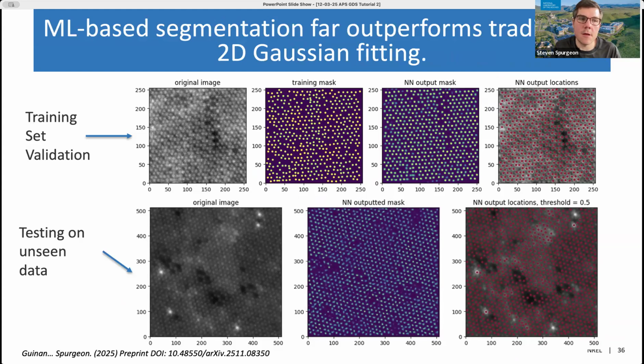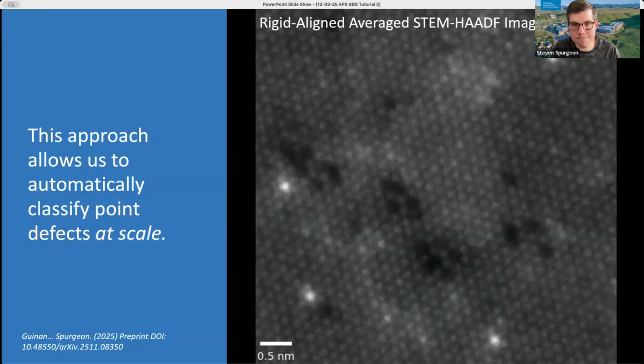And so what you're seeing here along the top is a training set validation looking at the input image, training mask, the output mask, and then the calculated positions. The bottom here is showing that we can test on unseen data and get really good performance relative to the 2D Gaussian fitting. And the key here is that this model scales. It scales to scenarios of noise, regions that might not be at the exact same orientation or illumination of the sample. And so this is a very powerful approach relative to the more brittle 2D Gaussian fitting.